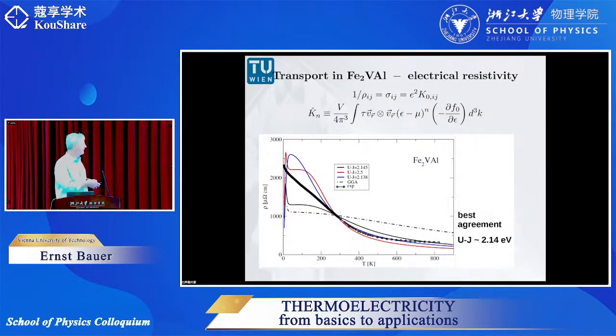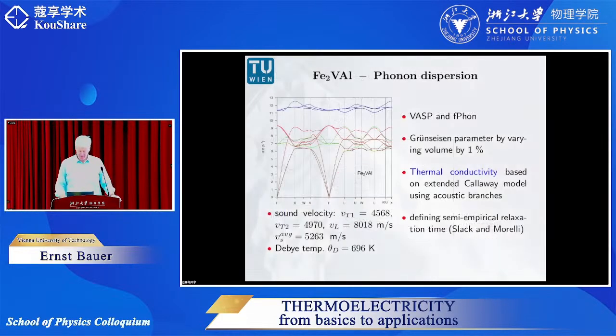Similarly, we can consider the electrical resistivity. Here is plotted the electrical resistivity as a function of temperature in a really broad range of temperatures, from 4 Kelvin to 900 Kelvin or something like this. By using, again, a constant relaxation time, one is able, at least at higher temperatures, to account for the temperature-dependent electrical resistivity. Even though we are using supercomputers, we are not really able to represent 100% the temperature dependence of important transport quantities which determine the thermoelectric power of a certain material.